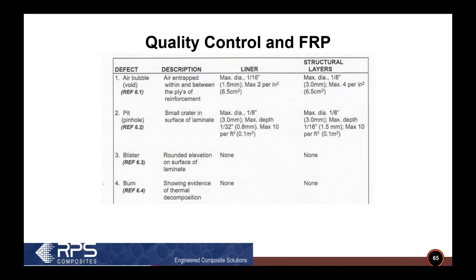You can see in the liner here we have a maximum of a 1/16 of an inch and a maximum of an 1/8 of an inch air bubble in the structure. And you can only have so many of those. And then there's other defects like pits and blisters and burns and cracks and crazing, and there's a whole list of them here. Some of those are none of them allowed, and others have certain criteria that are allowed. And this is what the QA people are looking for every day when they're inspecting the laminates.